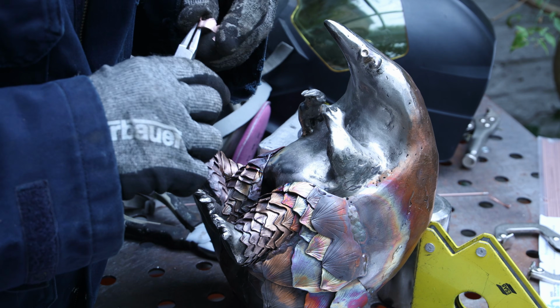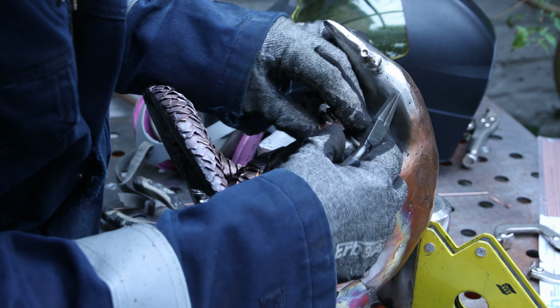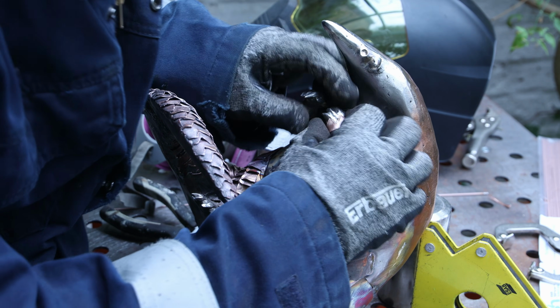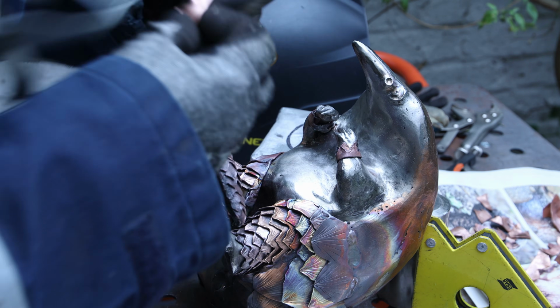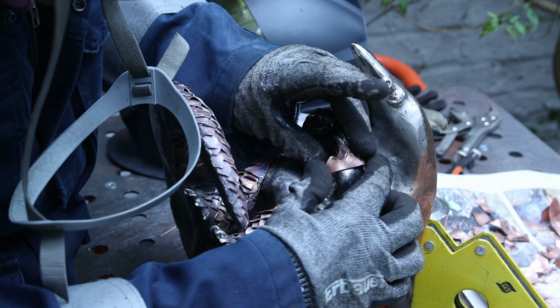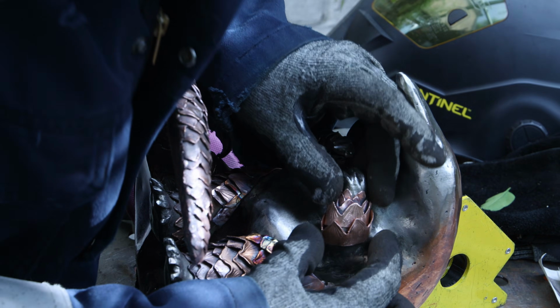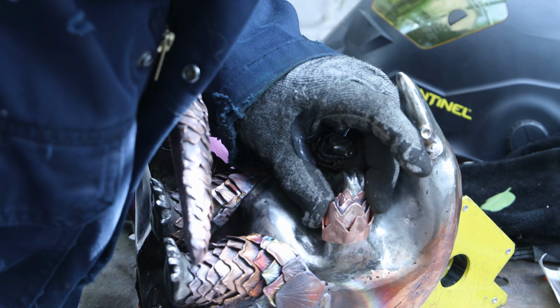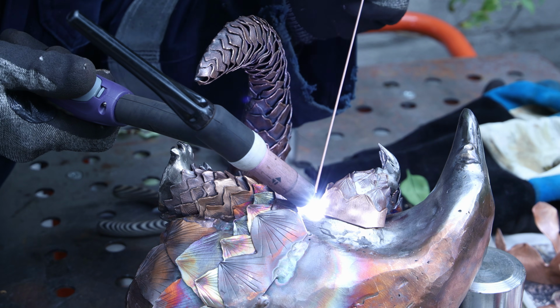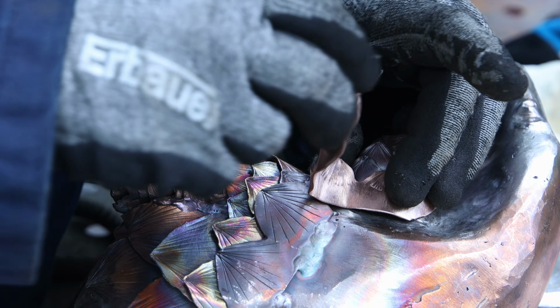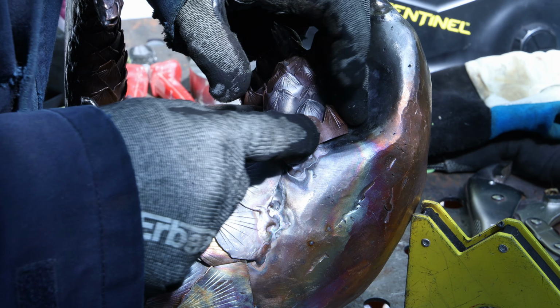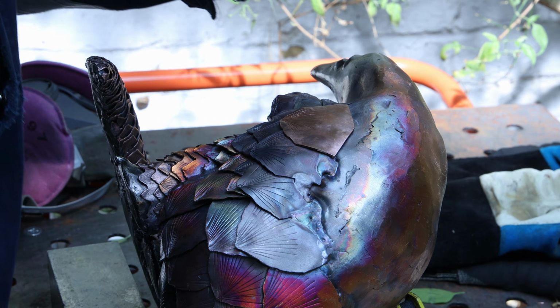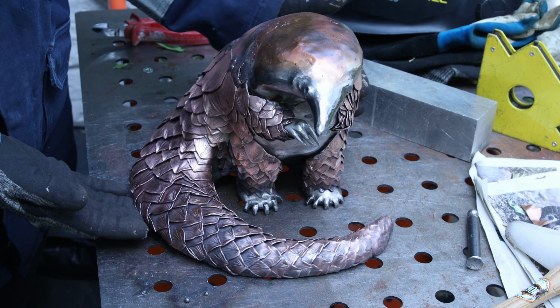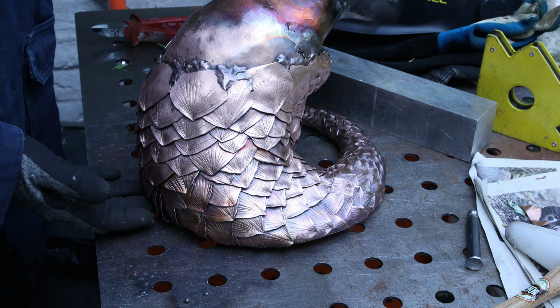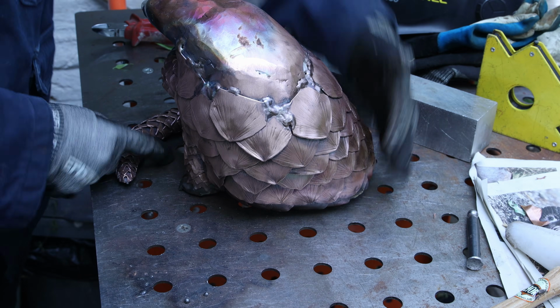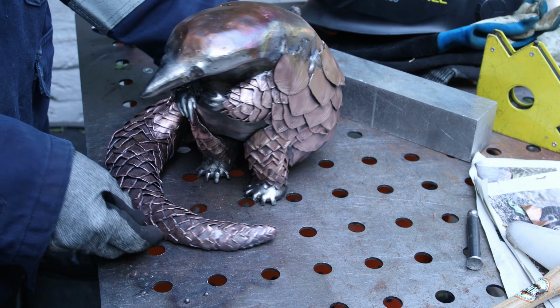Then I moved to the much smaller front paws, and that was the harder and trickier part because it was so damn small. And obviously I went down to the scale, had to really work with such a tiny proportion. And welding it was really hard because I used the TIG even below 20 amps. I was at 18 at some point and I had a really short window. If I stayed too long, poof, it would melt the copper. It was really hard. So I kept adding more and more scale. It seems like it was an endless need for more scale to be cut, shaped, and welded into place. It feels like I've done 1,000,000 scales for this sculpture.